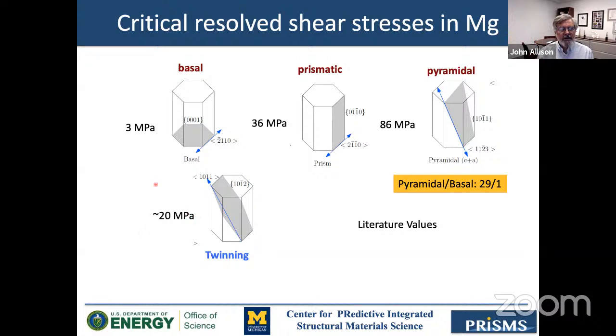Less clear is twinning. The literature sort of suggests it's around 20 MPa, but there's limited detailed literature around that. And so a lot of this has to do with calibration of crystal plasticity models. That's where a lot of this has been derived. I'll talk more about these values as we go, but I just wanted to set the stage around that.